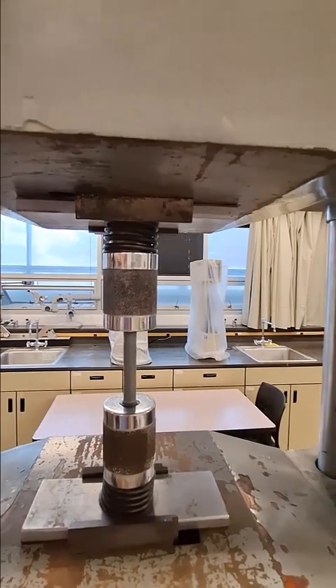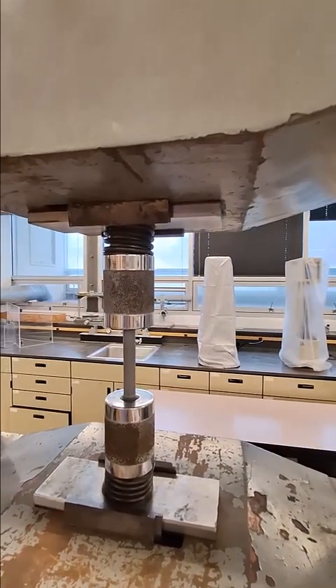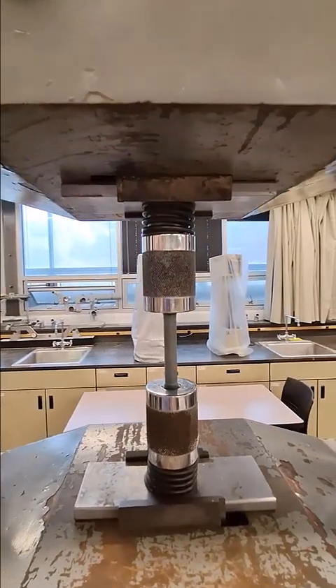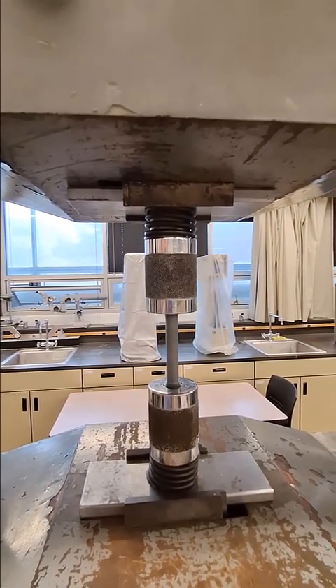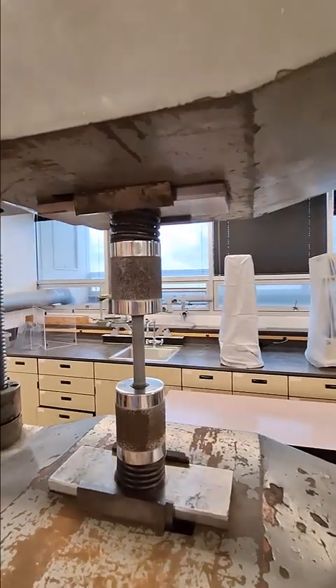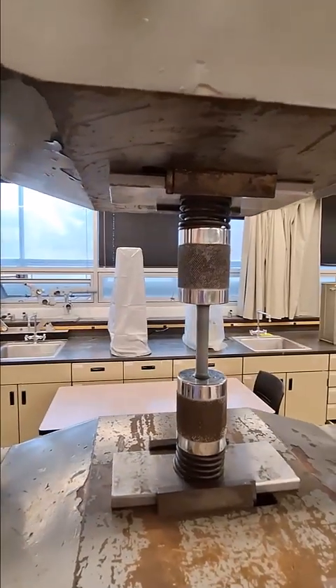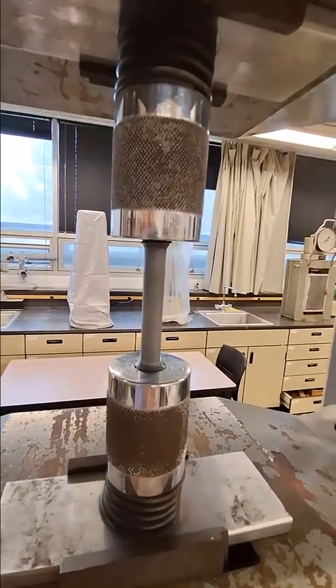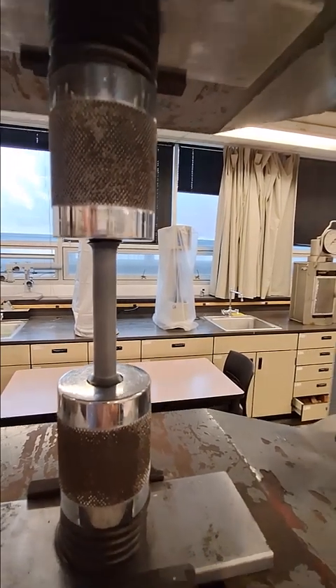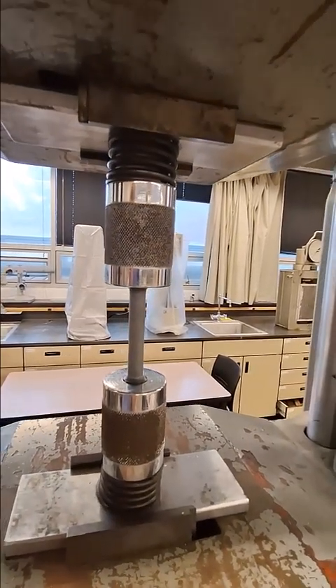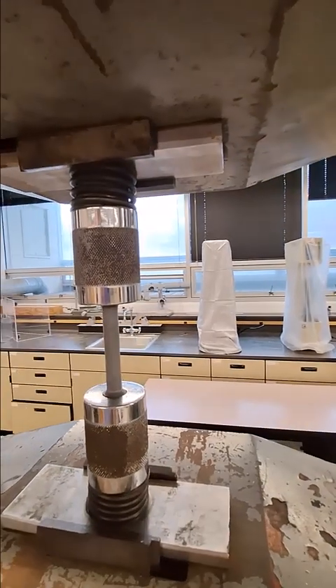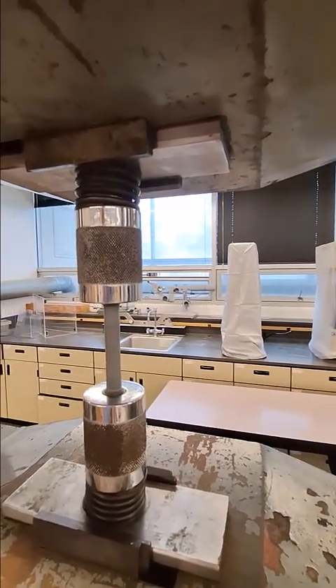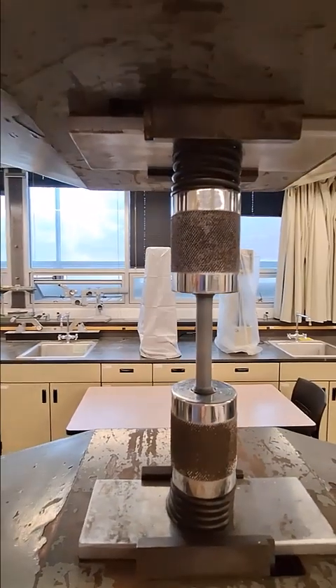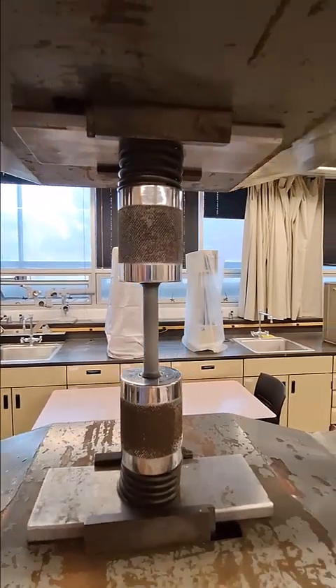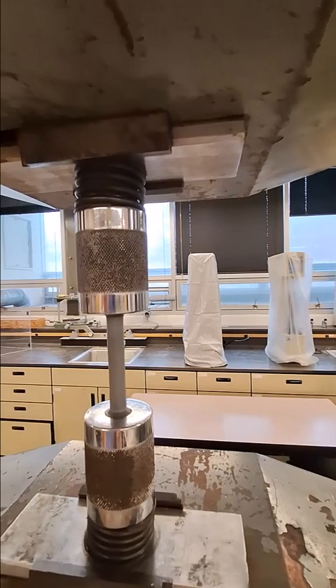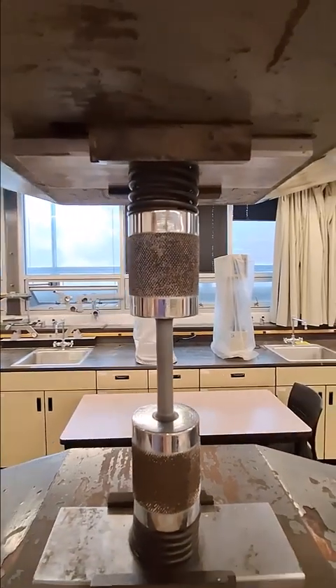But this is kind of the difference in polymeric materials versus metallic materials in terms of the mechanical properties. Obviously, polymers are, in general, much more ductile than metals. Even polystyrene, and actually, I don't know if you can see this here, the colors have started to shift too, because you're looking at essentially chain elongation and alignment that is not indicative of the fully amorphous polystyrene. So that is something to examine and look at. And you can almost see that neck starting to form here, but the color change is really interesting.